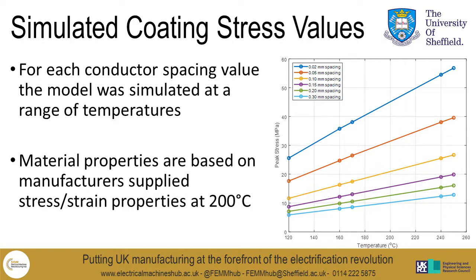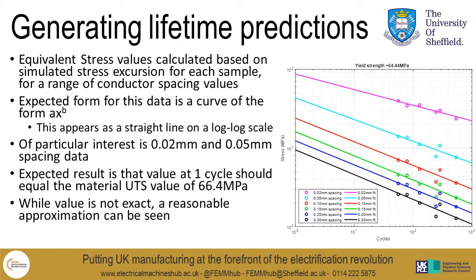Okay, so this slide shows the simulated coating stresses obtained for a range of different spacing values. You can see that the general form follows that of the previous model. The specific values vary, obviously due to the difference in geometry. The properties used here are the non-linear material stress strain properties from the manufacturer, assuming a 200 degree temperature. So based on the stress values from the previous slide, combined with the known temperature excursions of each sample, it's possible to determine what the equivalent stress for each of the test samples is.